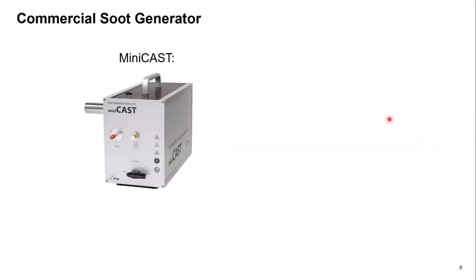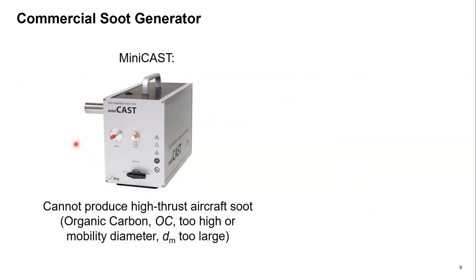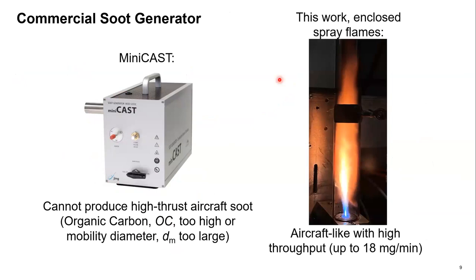In order to facilitate soot research, commercial soot generators are often used to produce soot in the laboratory so that we can study things more routinely and cheaply. From this, the miniCAST is one of the most well-known generators. However, it cannot produce soot similar to that of aircrafts at high thrusts. Specifically, if the OC is too high, then the mobility diameter tends to be too large, or vice versa. So what we did in this work was we used enclosed spray combustion of real jet fuel in order to produce aircraft-like soot at high throughputs, up to 18 milligrams per minute.